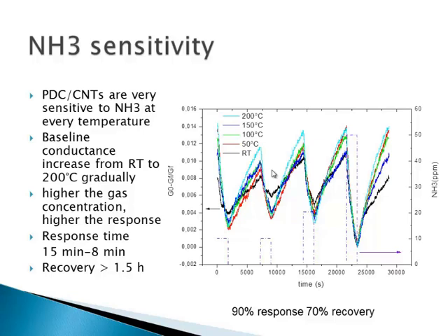Of course, the higher the gas concentration, the higher the response. We have response time. It's 15 minutes to 8 minutes, with 15 minutes, of course, at room temperature, and 8 minutes at higher temperatures. Still, the recovery is quite high. It's more than 1.5 hours.